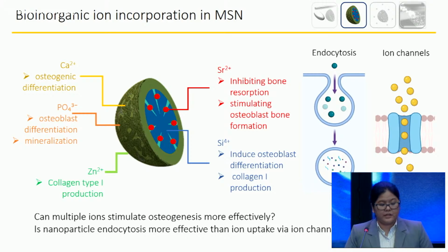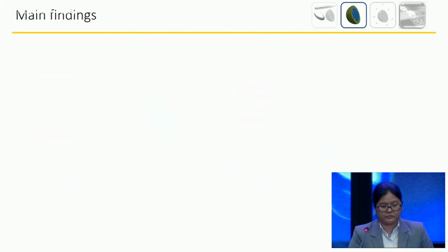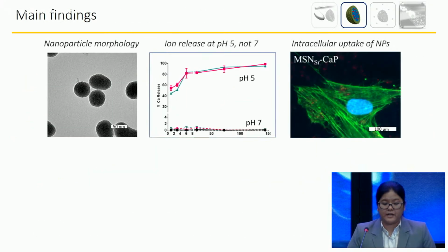So in this chapter, we want to investigate whether multiple ions can stimulate osteogenesis more effectively compared to a single ion, and whether nanoparticle endocytosis is more effective than ion uptake via the ion channel. We successfully synthesized the multiple ion-loaded mesoporous silica nanoparticle. It has shown pH-responsive release and intracellular uptake in the HMSC.